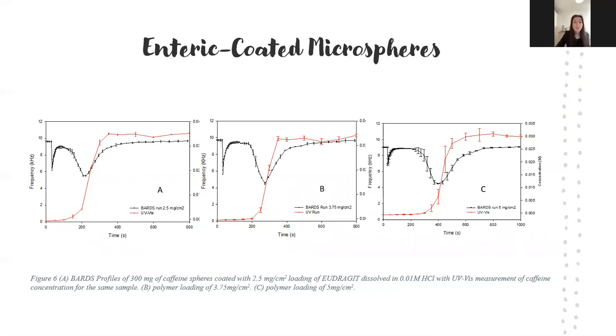So this figure 6 shows the profile of caffeine samples of various coating thicknesses of EUDRAGIT, a functional taste masking polymer. The black profile represents BARDS data, while the red profile represents the UV-Vis data. Data shows that the coating polymer is behaving according to its desired purpose. The UV-Vis data shows the concentration of caffeine is close to 0 during this lag time phase.